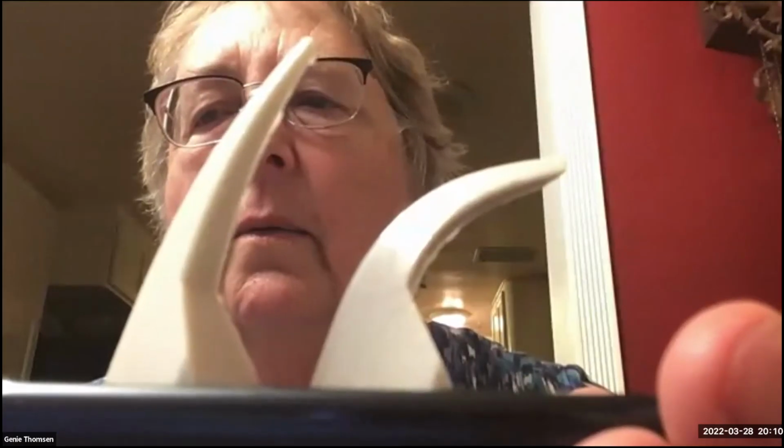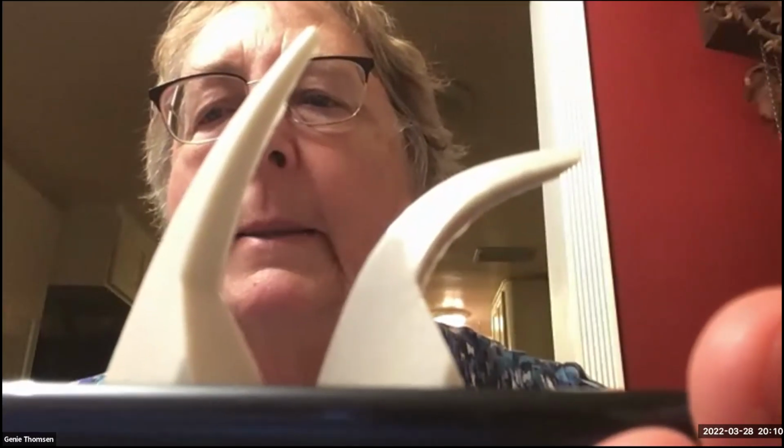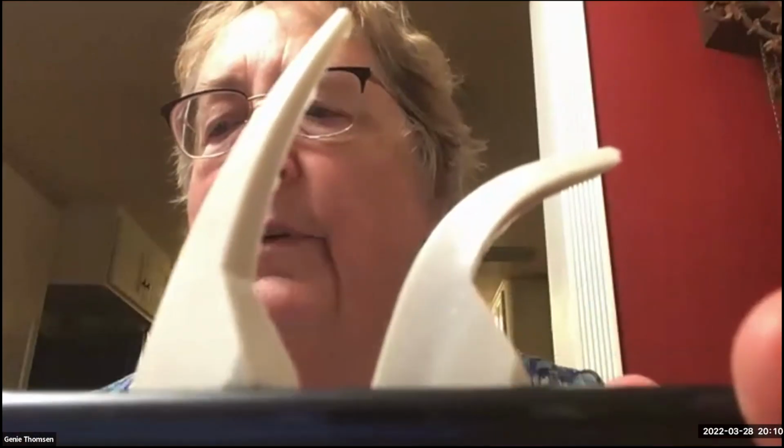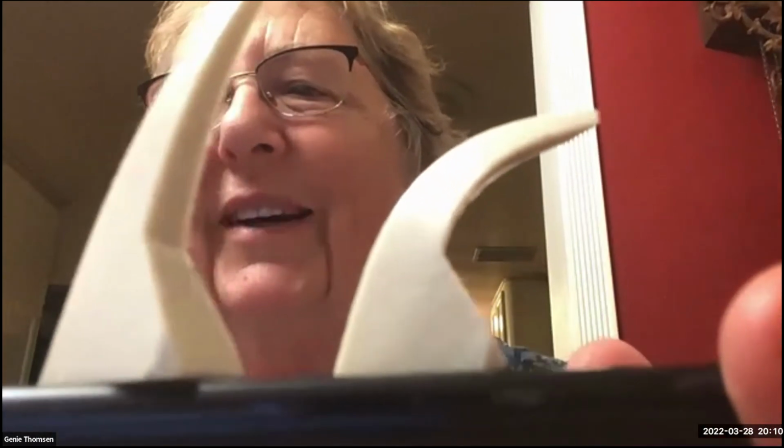That 5 that you've got right there, if you put a 10-minute hold on it, if you added another 5 to 6 minutes, that would be down to the 6 o'clock position. And then that's where the 6 should be then. Yeah, or you could increase your temperature to get that to come down by about 4 or 5 degrees, and you either get it through increased temperature or extended time. Okay. It was my first time testing the kiln to see if it was firing to what it was supposed to say it was doing.